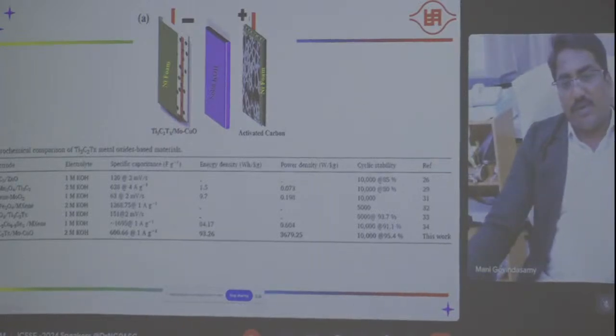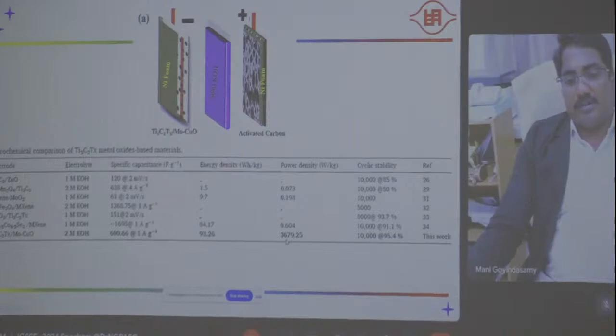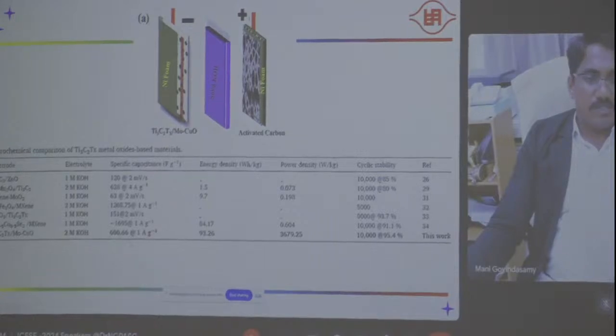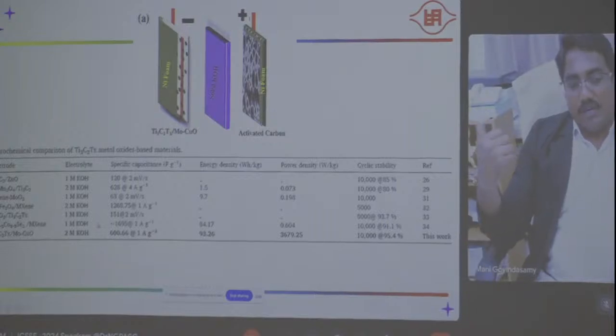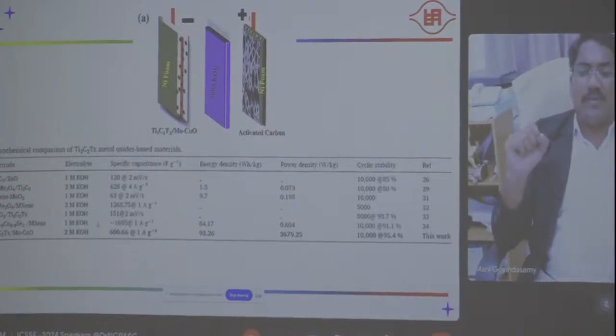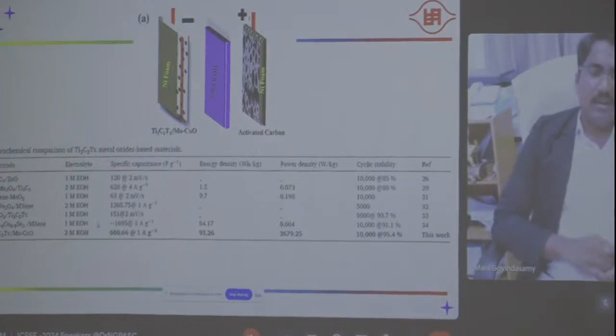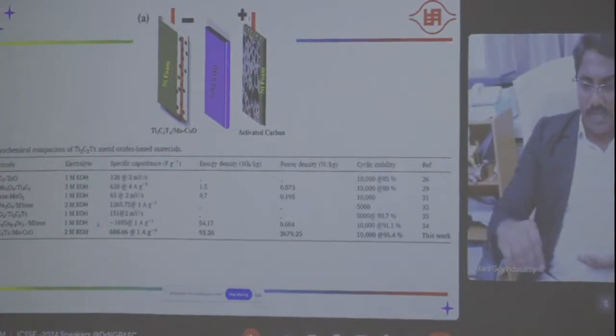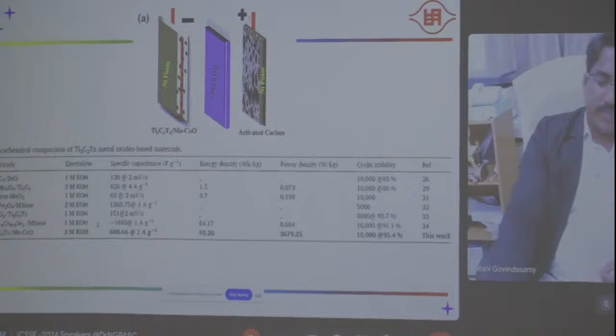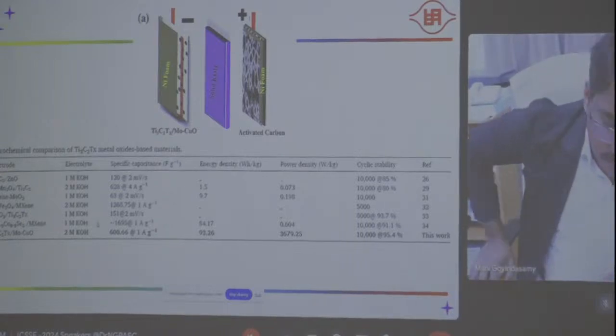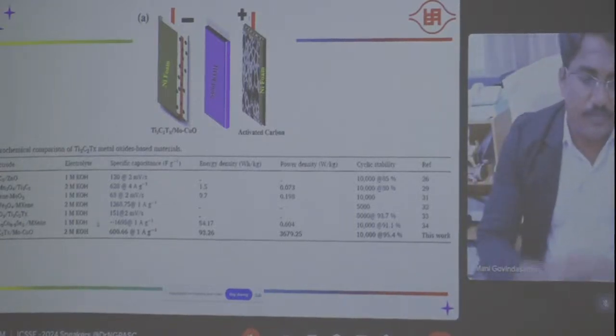In this device, the power density we obtained is more than 3,000 watts per kilogram. We can get even 95% cyclic stability over 10,000 cycles, and the specific capacitance is 600. And we used KOH, similar to the previous work, the potassium hydroxide. So far in my lab we are using KOH as a standard electrolyte for supercapacitor applications. Also we are developing hybrid supercapacitors.